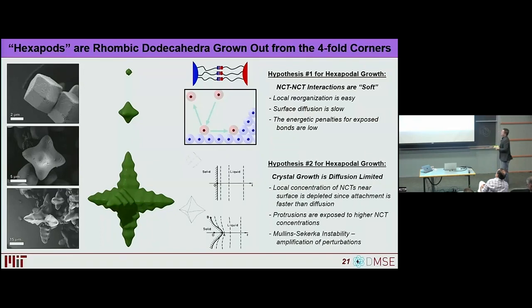The other thing that we think is going on is what's referred to as a Mullins-Sekerka instability. This is a diffusion-limited process, meaning that right at the surface there's going to be a depleted region where we have a lower concentration of particles, because they've now collapsed onto the surface. So if I have any sort of perturbation that points out into the liquid where the concentration is higher, that perturbation is going to be exposed to a higher concentration of particles, and so we get this runaway effect where the particles deposit more rapidly on this perturbation, and the perturbation preferentially grows. So essentially what we think is going on is the particles start out in a pseudo-spherical case. They can pretty easily reorganize into something that is rhombic dodecahedra-like, but as it gets bigger and bigger and bigger, the driving force to get to that perfect rhombic dodecahedra goes away, and as a result, any sort of perturbation that arises tends to be propagating.